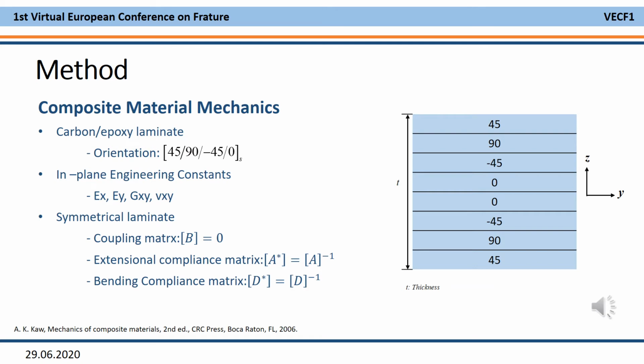Carbon epoxy laminate is analyzed. The orientation is given. The laminate has 8 plies and is symmetric. In-plane engineering constants are calculated for the bond-based peridynamic code and finite element method. In-plane engineering constants are the engineering constants in the global coordinates. The constants are calculated from the extensional compliance matrix.